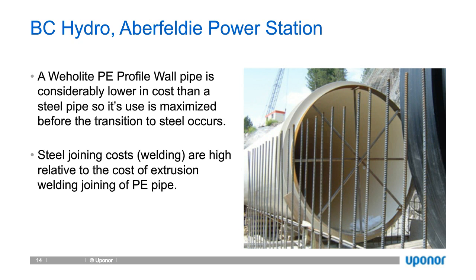When we talk about joining on the Weholite, the use of a term like welding is a bit of a misnomer, because normally in welding there's a change of state from solid to liquid and then back to solid again. And in steel welding, the various elements in the steel alloy convert back from liquid to solid at different temperatures as the joint cools. And that's, of course, the heat affected zone. And it's in the heat affected zone where the chemistry is changed, where there's a reduced resistance to corrosion. That's the location where much of the corrosion in steel pipelines will occur.